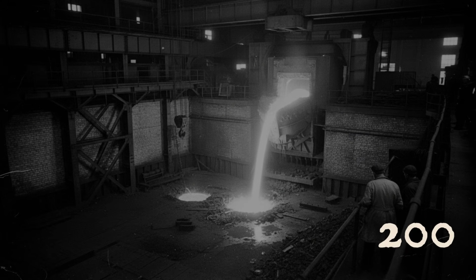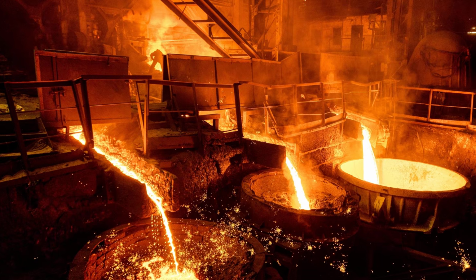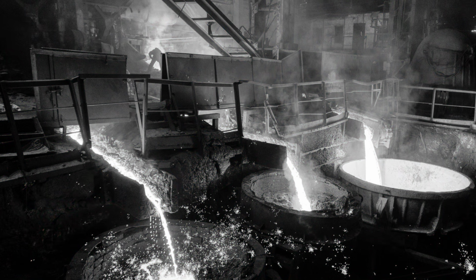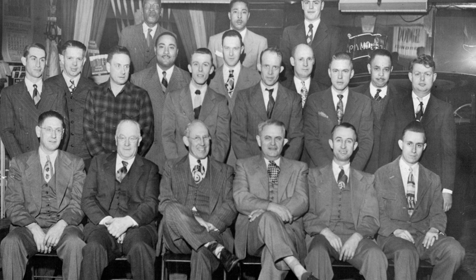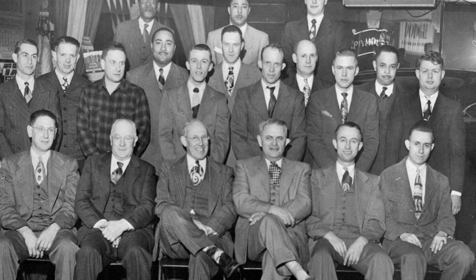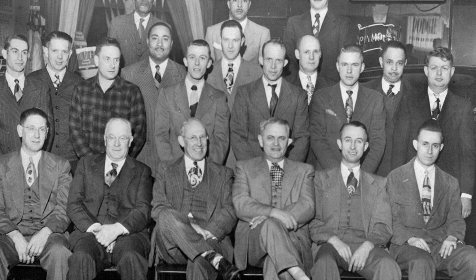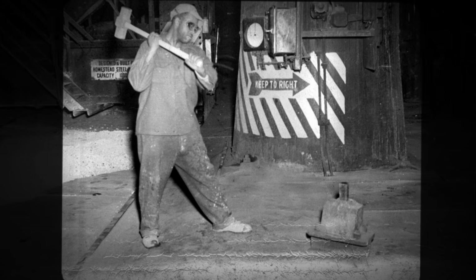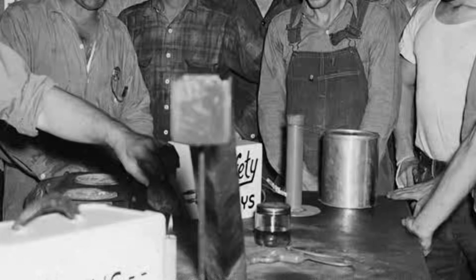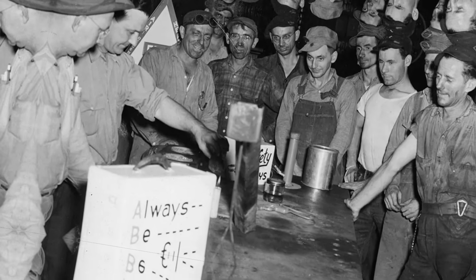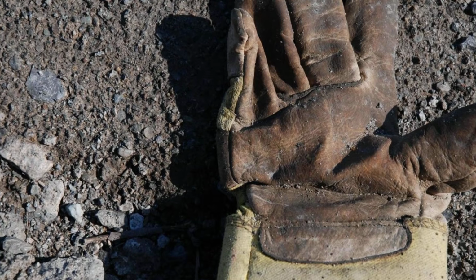The entire heat, 200 tons of liquid steel at 2,900 degrees Fahrenheit, poured through the tap hole and into an empty pit and spread across the floor of the ladle bay as a catastrophic molten puddle. Fields was a capable enough foreman that the incident, which in most industries would have ended a career, resulted in him being given a different supervisory position at a comparable level. Steel mills in that era lost equipment and floor space to liquid metal with enough regularity that systems of response existed for it. But that does not mean the people in the vicinity were safe while it was happening.